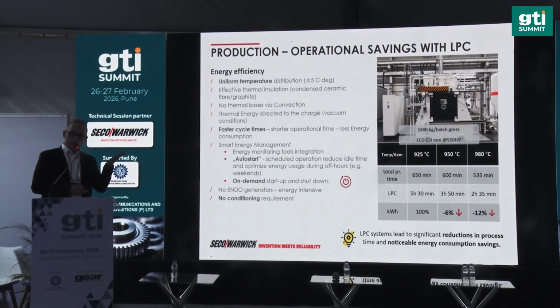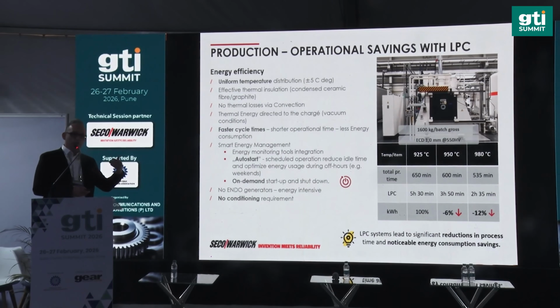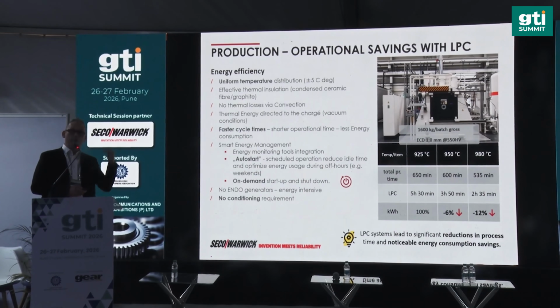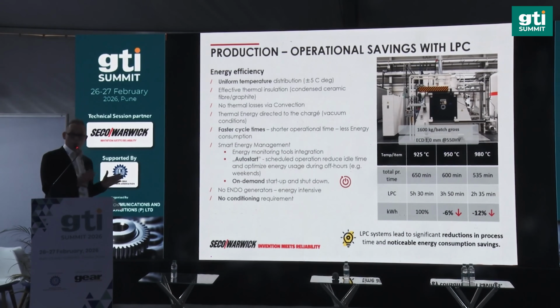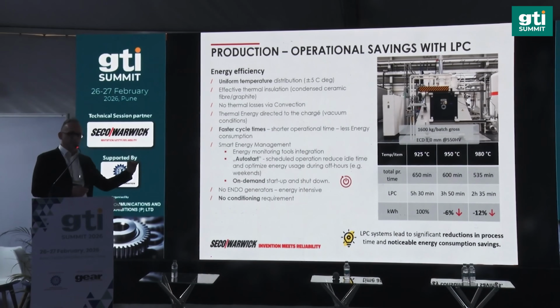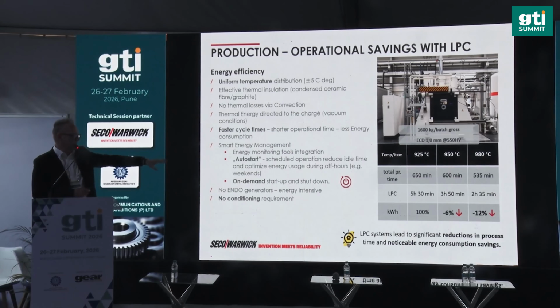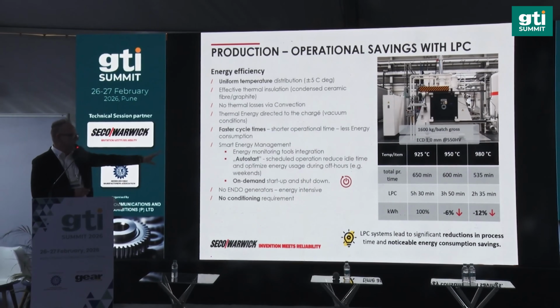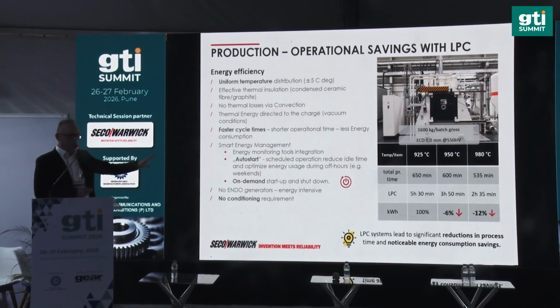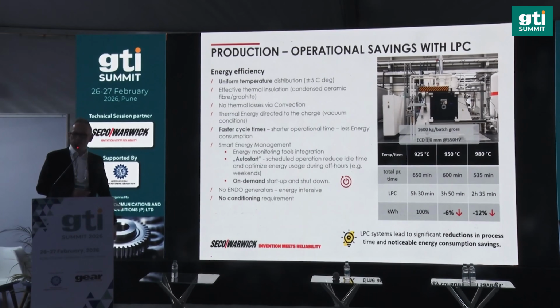So if we would go up with the higher temperature, you tend to think that, okay, we would have to give more energy, and that's true because we need to utilize higher temperatures for processing. However, as we are shortening the overall process time, we are actually saving in this aspect also. In a short comparison, if you would go up to 950 for this particular case depth of 1 millimeter, you would reduce the energy consumption by about 6%. And if you would increase to 980, you would even reach more than 10% savings.